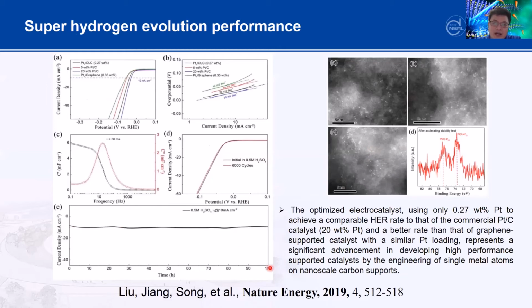As you can see, this is a 100 hours stability test. If you do not have any chemical bonding in here, if you do not understand how chemical bonding can control this single atom, it will be lost during the reaction. The second very important thing is we found that with the optimized electrocatalyst, you only use about 0.27 wt% Pt combined with the carbon support. You can reach a very comparable HER rate, which is really similar to the 20% Pt loading. So that means you really decrease the noble metal about 100 times. So this is a really economic way with a high rate.